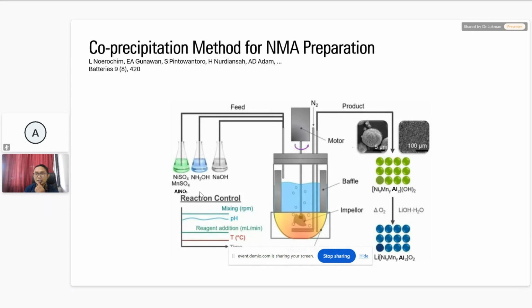And also the motor speed, the RPM, has an effect on the morphology and the particle size. That also we have to make sure of, because the solution will become thicker after 2 or 5 hours. Then the power of the motor should be enough to rotate the plate or impeller inside of this reactor.